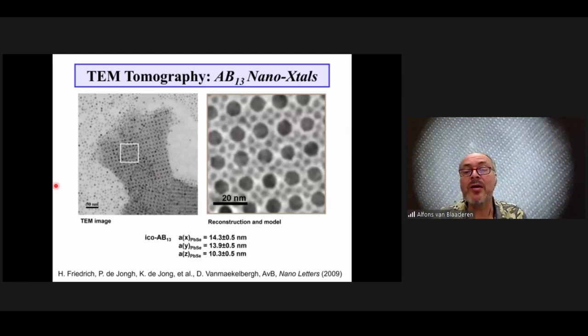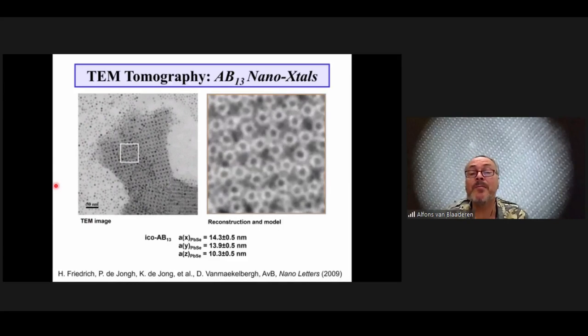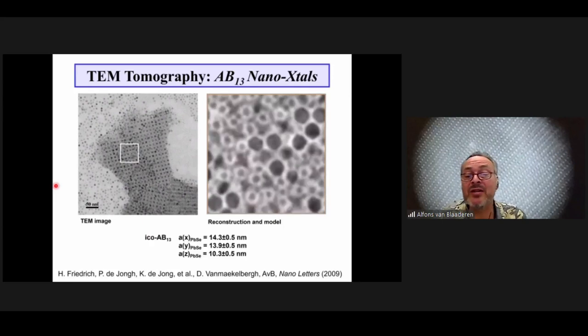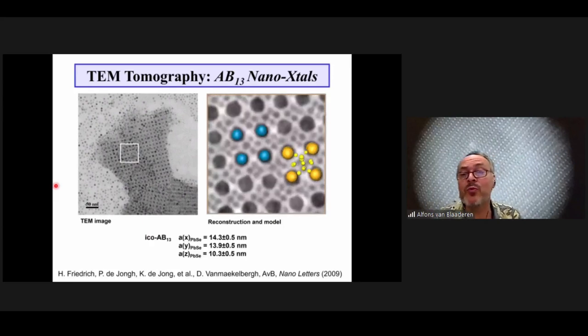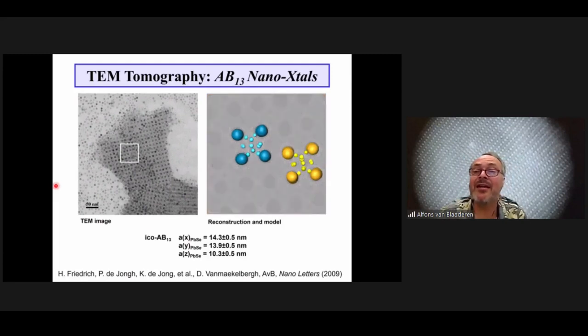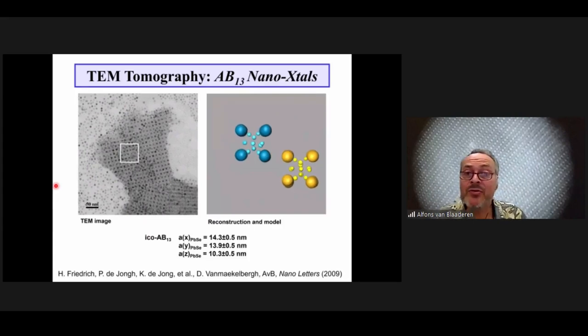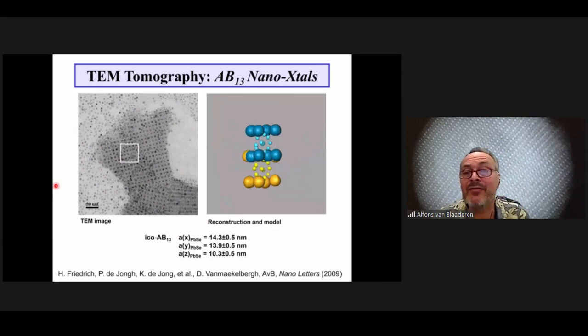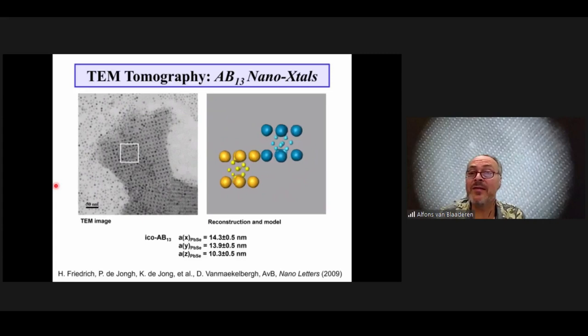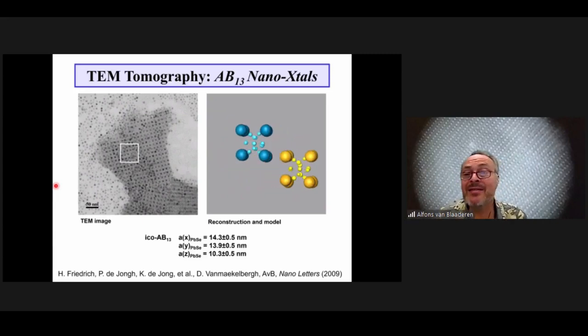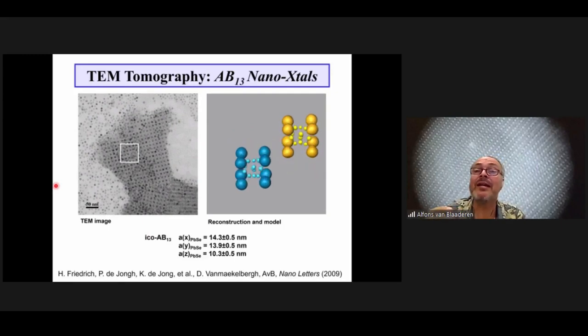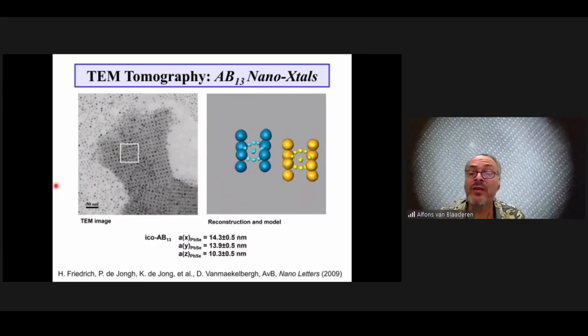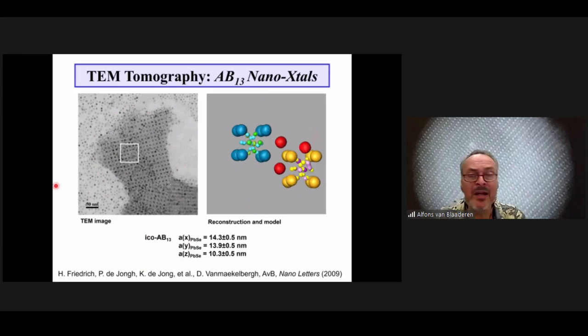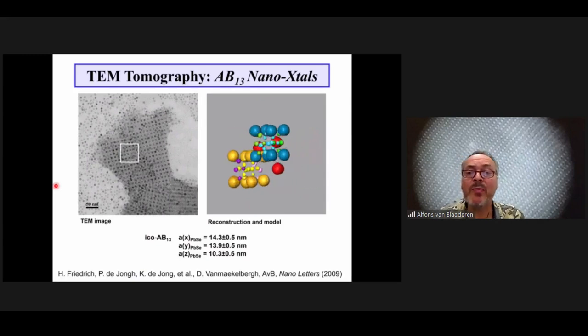Marjolein, you mentioned yesterday this beautiful binary crystal, which forms when the size ratio of the big and the small particles is about 1 to 3. With scattering, you cannot really analyze what the structure of the small particles is. But by doing tomography, and this was work done about 10, 11 years ago in the Debye Institute, we found that there are not only simple cubic lattices of the big particles, which have 3 times the size, but that the small particles have been arranged on an icosahedral lattice with an icosahedral symmetry around the big particles on the cubic lattice. So we can now also identify single nanoparticles with sizes of 10 nanometers in 3-dimensional data sets.